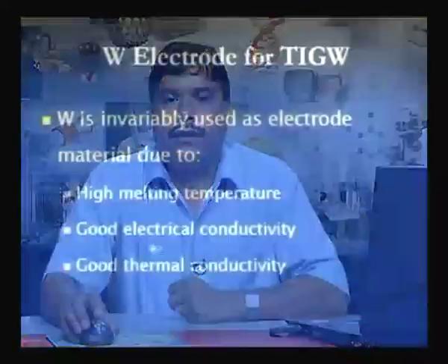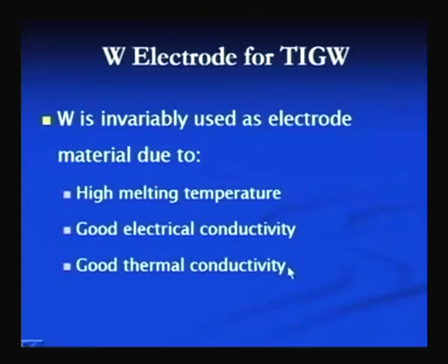Thermal conductivity is also important, because heat generated at the electrode tip has to be transferred effectively to maintain its temperature and reduce its degradation. So, good thermal conductivity, good electrical conductivity and high melting point are the important points because of which it is selected. And one more important point in the selection of the tungsten material as an electrode is its good electron